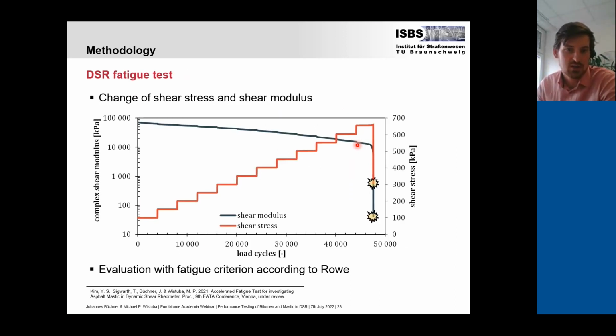For the intermediate temperature range, we tried a lot and used tests which are available, but we're quite unhappy. So this is what we came up with. We use a constant shear stress test, but the shear stress, as you can see here, is stepwise increased during the test in order to allow an accelerated fatigue test. This is one of the main issues with fatigue tests. They require a lot of time. And we don't have so much time, and we don't want to wait 1 day for one test result.